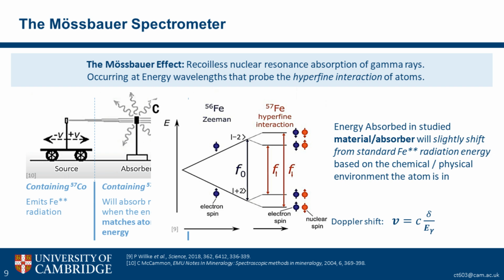So to understand how a Mossbauer spectra looks like, I'll quickly talk you through how a Mossbauer spectrometer works. Since we're looking at gamma rays, we start with a radioactively decaying isotope of cobalt-57. And this will emit a radiation energy that we're interested in, and we'll call it Fe star star for simplicity. And these gamma rays of Fe star star radiation are passed through and shine onto our sample or absorber, where the sample that we're trying to study will be placed. And the iron 57 isotopes sitting inside our sample will absorb the gamma rays when the energy of the gamma ray matches the energy of the iron inside our sample.